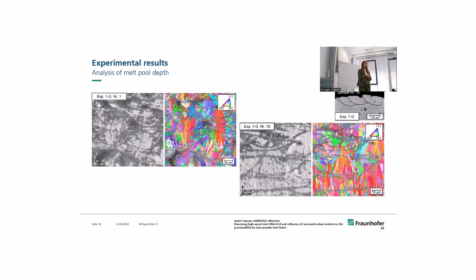The hardness was very pronounced. You can really see the difference there. With the EBSD image, you can see a difference as well. So you have the sample number 1 with the deeper melt pool depth in the middle of the part. You look at this, you still see the epitaxial grain growth, but little larger grains maybe. And with the sample 15 with the wider or shallower melt pools, you see smaller grains mostly, and a more pronounced grain growth in the direction.